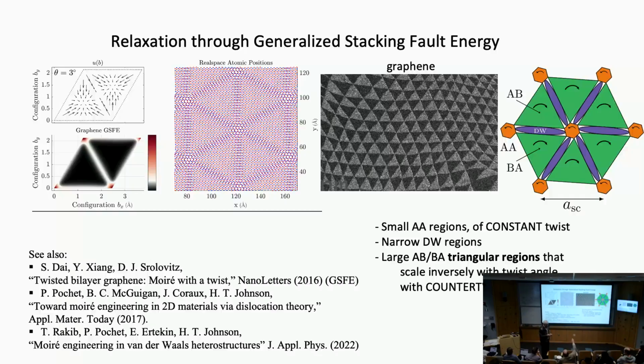And the density of this blackness, what does it mean physically? Okay. The reason why one is white and the other is black is because this is scanning transmission electron microscopy, so it's done not exactly perpendicular, but slightly off. So one of them looks a little bit brighter, and electrons can go through easier, and the other darker because of the slight off. And that's how you see the two different. But from the theory point of view, they should have exactly the same. They're equivalent, yes, exactly. But because the slight deviation from being normal breaks that symmetry, you see slightly different.